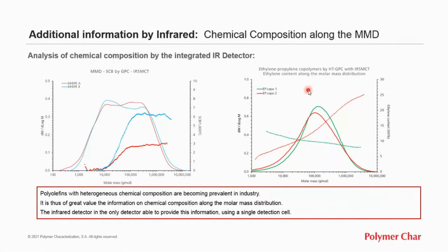With the current trend in industry towards more complex heterogeneous products, the information on chemical composition against molar mass is really of great value. Here we see two representative examples. On the left-hand side, we see the analysis of two similar bimodal high-density polyethylene products with a small amount of short chain branching added in the high molar mass fraction. Short chain branching we can read in this graph. One of them was 3 short chain branches, the other around 6 short chain branches per 1,000 carbons.